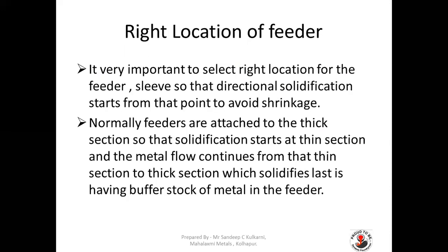Right location of feeder is also important. Select the right location so that directional solidification starts from that point to avoid shrinkage. Normally feeders are attached to the thick section so that solidification starts at the thin section and metal flow continues from thin to thick section. The thick section, which solidifies last, has a buffer stock of metal in the feeder, ensuring enough volume to fill the metal requirement at the end of solidification.